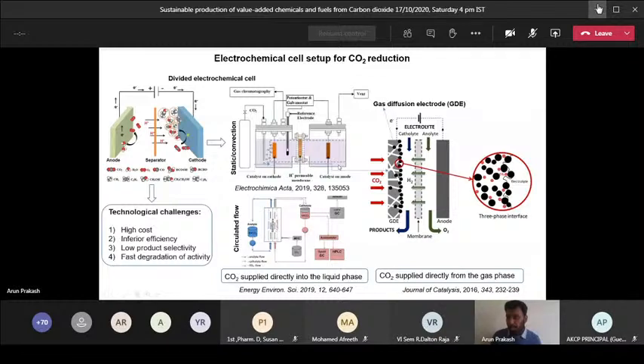Okay. And the effective concentration of dissolved CO2. So you may have a lot of carbon dioxide in your bulk electrolyte, but that will not react with your electrode. So only the carbon dioxide which diffuses and moves near your electrode and that electrolyte interface at which carbon dioxide reacts will only account for the CO2 reduction. This you have to bear in mind. That's the reason for using a gas diffusion electrode.